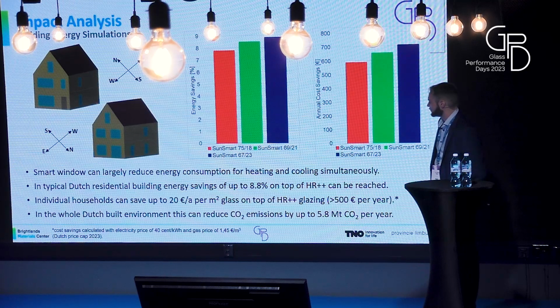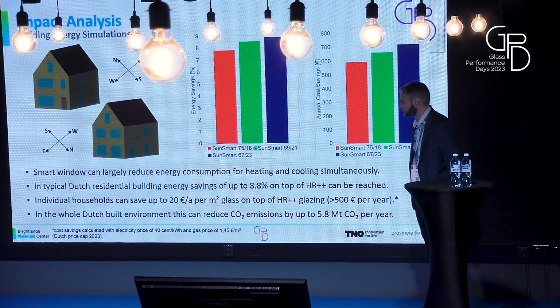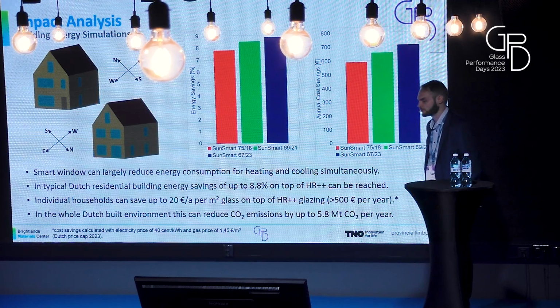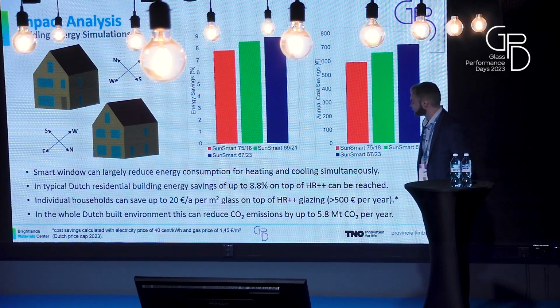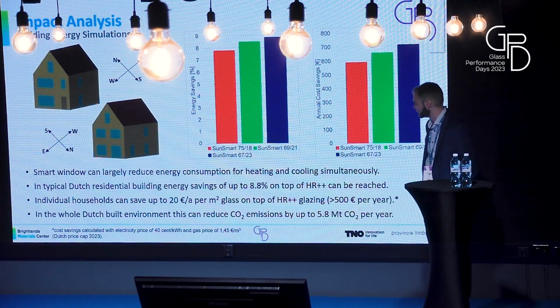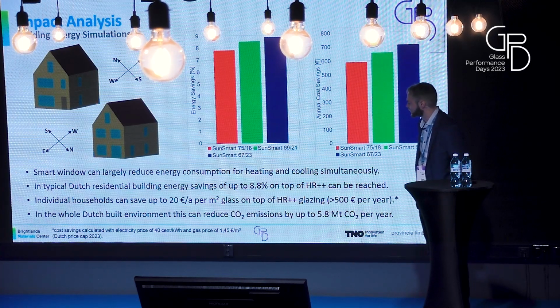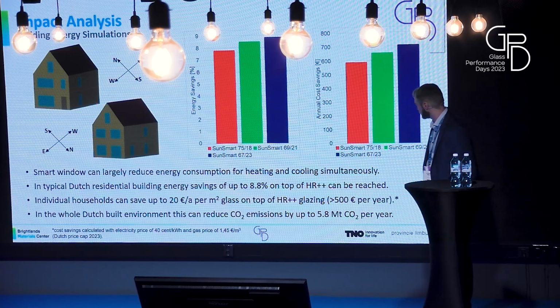And that means with the current energy prices in the Netherlands that you can save up to 20 euros per square meter glass per year on your energy bill. And to just put that a little bit into balance of the costs of the material, we're currently talking about material costs and application costs of something like 3 to 5 euros per square meter. So there you already have quite a good impact on your energy demand at a very low price of the material.